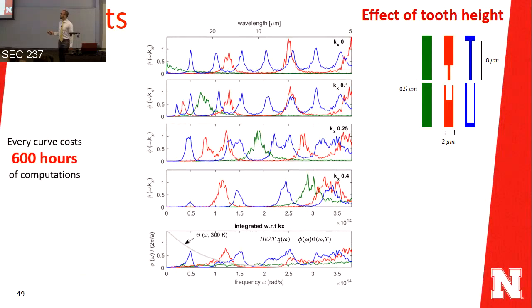To appreciate the effect of tooth height, we made the simulation for 3 cases: flat surface, 3 micron tooth height, and 8 micron tooth height. We have calculated the transmission factor for different values of the Bloch wave vector of 0.1, 0.25, and so on. And here in the last panel is the integrated transmission factor with respect to kx.